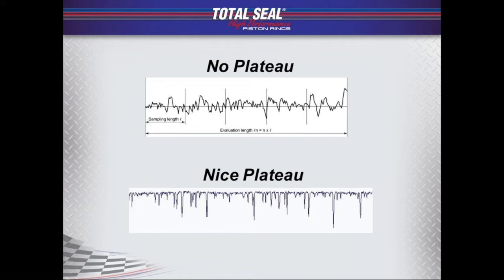Well, sometimes it's the ring, but generally it was a cylinder finish issue. The cylinder simply didn't have a good plateau. And it takes time for that ring to wear that plateau in. And it will do that naturally through the running process. And again, with soft blocks, softer rings, big rings, lots of tension, it's going to do it relatively quickly, but not so much with today's stuff. That's why it's so very, very important to have access to one of these, the profilometer, so you can actually measure that finish and make sure you're getting that plateau.